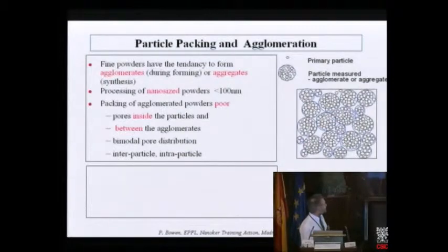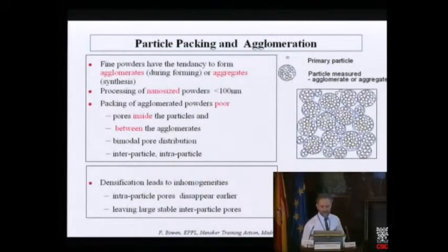I mean, whether it's an agglomerate during forming or aggregates from synthesis. If we pack these, we have pores within the aggregate, and between the aggregates we have a bimodal pore size distribution. If we then try and sinter, we densify depending on the packing: in the aggregate we can densify, between the aggregates we don't, and we see the type of defects that I showed you with the alpha alumina, with the tail of aggregates a few slides ago. So the problem is you get these stable interparticle pores, which you can never get rid of.